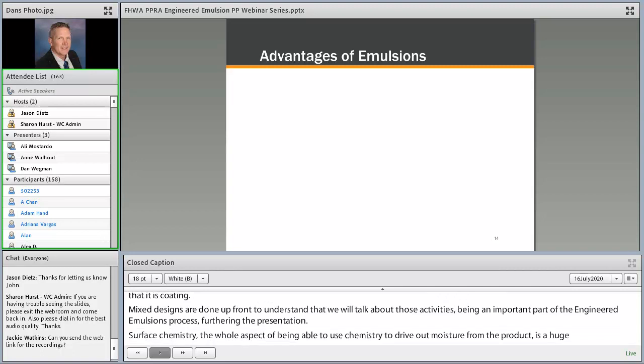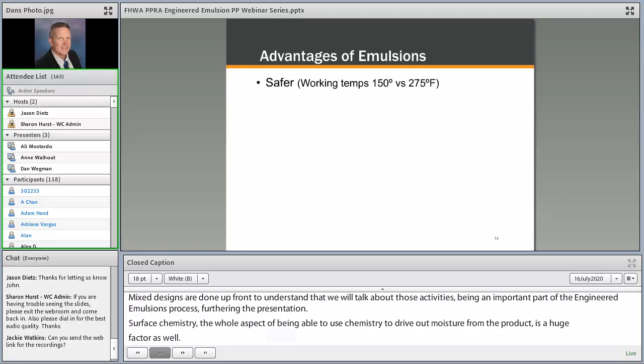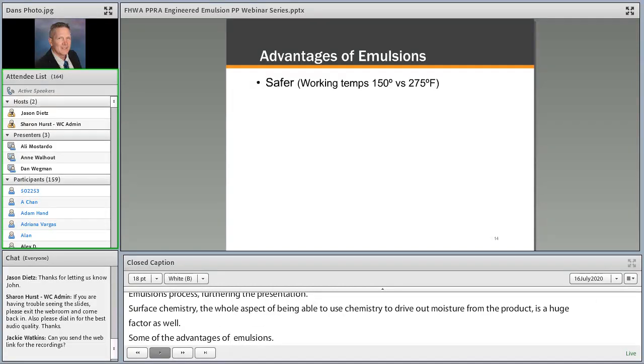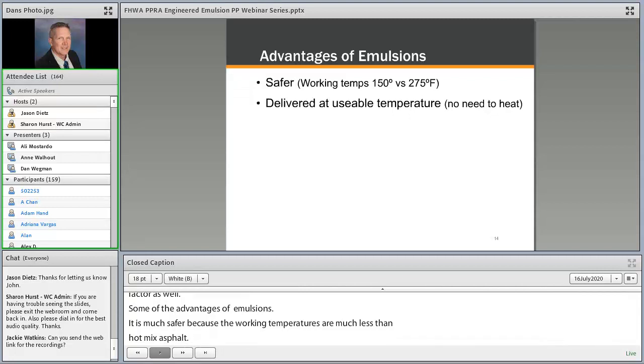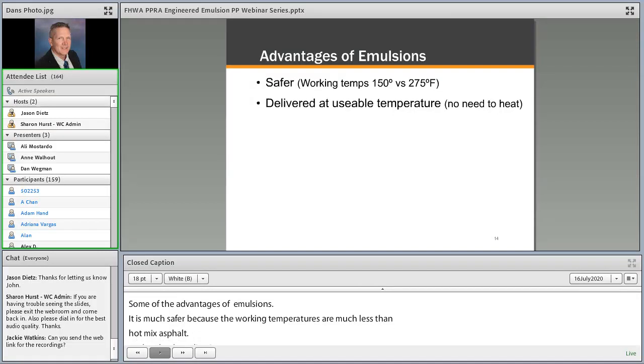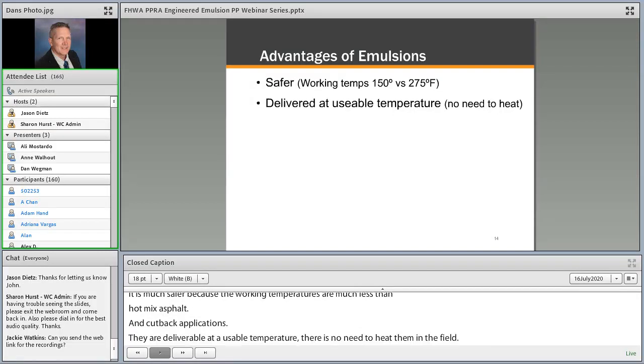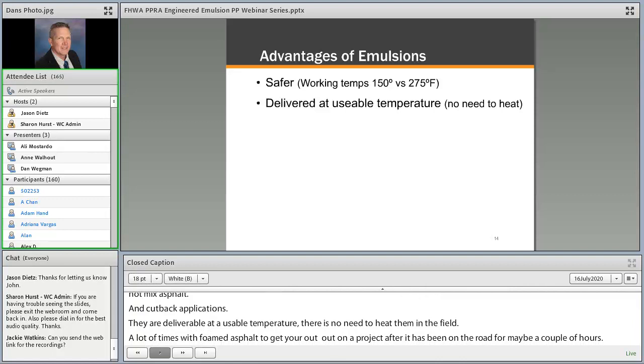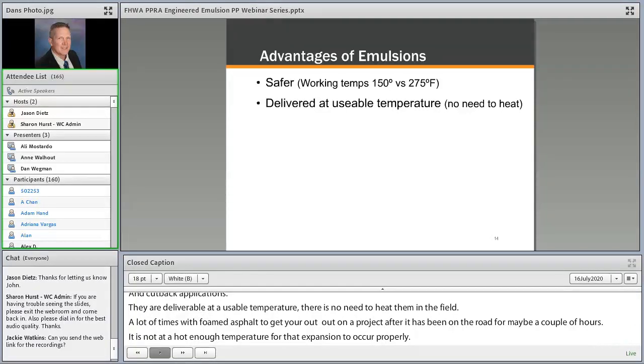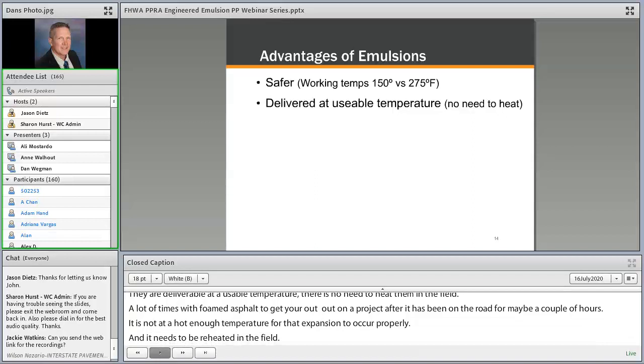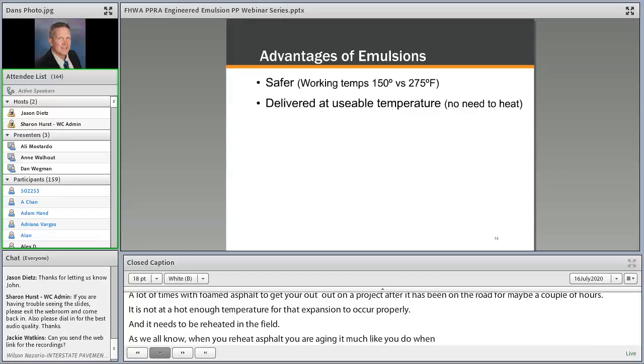Some of the advantages of emulsions: they are much safer because the working temperatures are much less than hot mix asphalt and cutback applications. They are deliverable at a usable temperature. There's no need to heat them in the field. A lot of times with foamed asphalt, you get your asphalt out on a project after it's been on the road for maybe a couple hours, and it's not at a hot enough temperature for that expansion to occur properly, and it needs to be reheated in the field. And as we all know, when you reheat asphalt, you're basically aging it, much like you do when you look at the rolling thin film oven test with hot mix. You're doing some short-term aging that makes the asphalt more brittle and more prone to cracking.